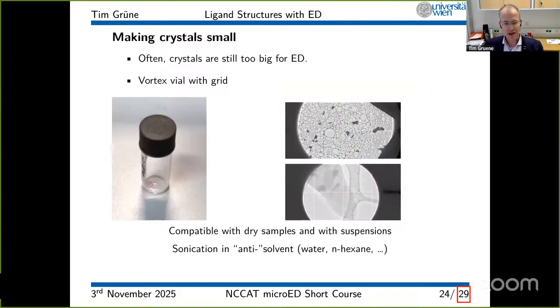In order to get there, there are several possibilities. In this case, we used an old grid or an empty grid as a mortar, basically. We put the grid inside of the vial and we vortexed it with the grid. The grid gets destroyed, so we cannot use that very grid because the lacy carbon is being ripped off during that process. But then we could use a new grid and pick up very, very small and faint crystals. And this is what the grids look like. You see they're really, really thin, and you can easily see through the graphene. And if you look here, they nearly have the same contrast, so it's an organic compound.